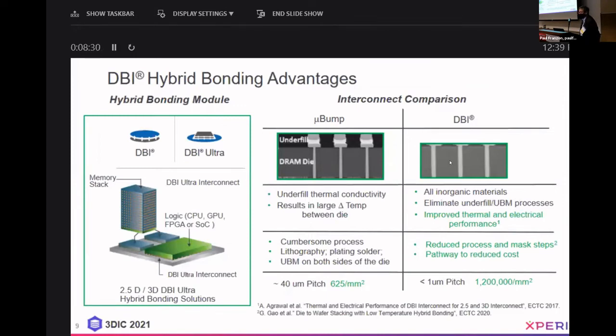In looking at the advantages of the hybrid bonding over microbumps, one of the big advantages is that there's no underfill needed for the technology. So this helps tremendously with the thermal issues. And also there's improved electrical performance from the copper to copper bonding. The microbumps have more of a cumbersome process with lithography and solder plating, whereas the DBI copper to copper bonding reduces process steps and mask steps and provides a pathway to reduce cost. And one of the biggest advantages is that the pitch that can be achieved can allow up to over 1 million connections per millimeter squared, whereas microbumps are going to be limited in that range.